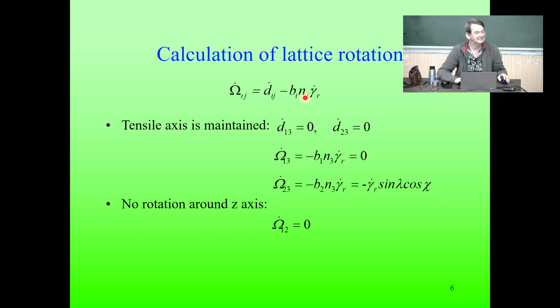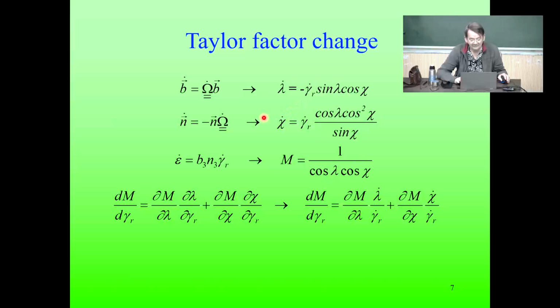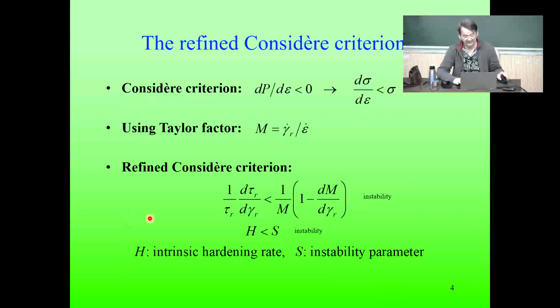Now, in the next slide, there's a change in the Taylor factor. Suppose I am starting with the ideal orientation for a given deformation. If the orientation is not changing, the Taylor factor will also not change. Exactly. So for a stable orientation, the m value will be constant, so dm d gamma r will be 0. And then if we go back to here, this is 0 here, and we only have 1 over m. And this is what defines the stability of a stable orientation. Precisely. But here, what you look at is single slip.